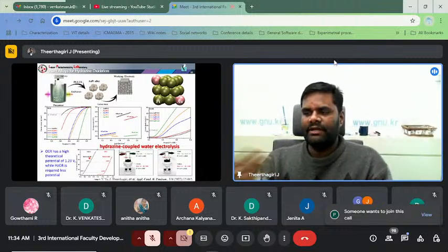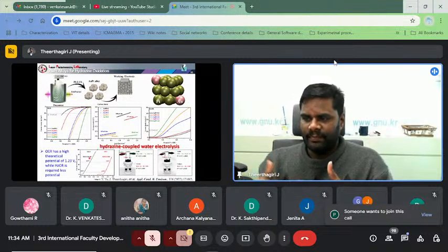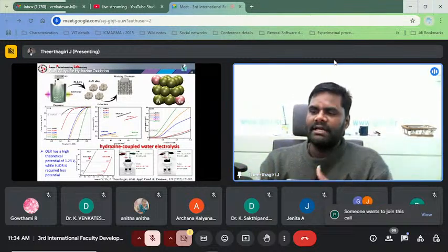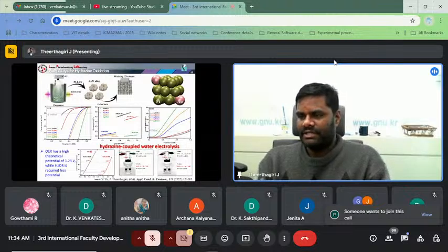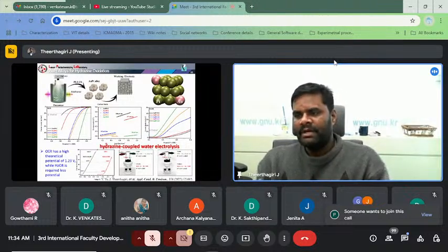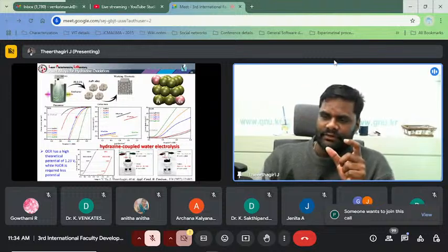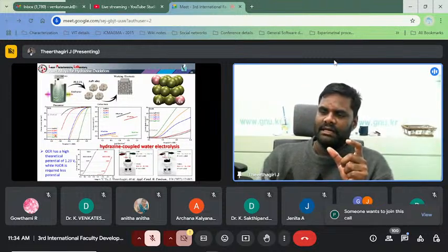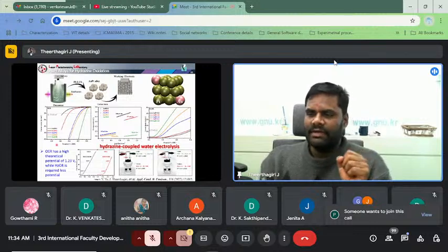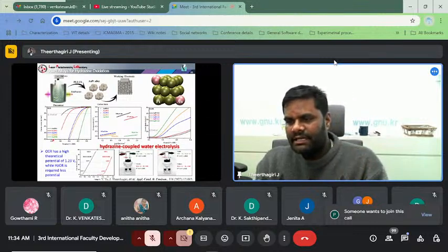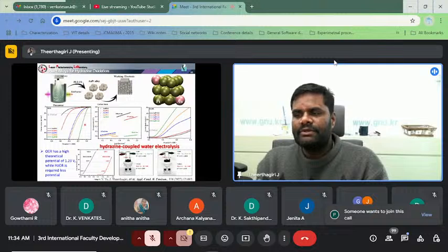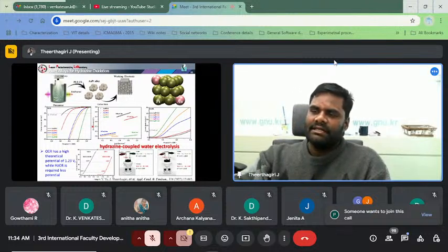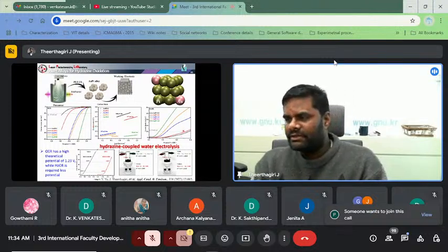This is the beauty of our work: replacing OER with small molecule oxidation. So this is the concept of this work. We studied different ratios of Au and Pt, almost 5 combinations, and we could see that the highest Pt ratio shows the highest HER activity. The highest HER activity also shows in hydrazine oxidation.